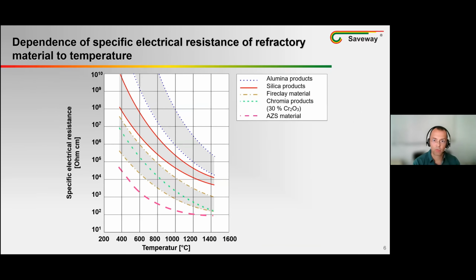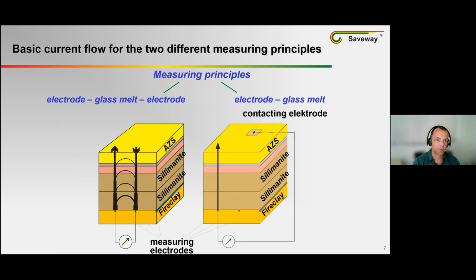For monitoring the remaining wall thickness of melting vessels, we use the physical quantity of the electrical resistance of the various lining materials. All materials shown here significantly reduce their electrical resistance with increasing heating. We can work with 2 measuring paths. One, comb-shaped sensors form one pole each, and the measuring current passes through the layers of the refractory material. In the principle shown on the left, a net-shaped sensor, similar to a structural steel mat, forms one pole above the lowest brick layer, and the contacted molten glass forms the second pole.